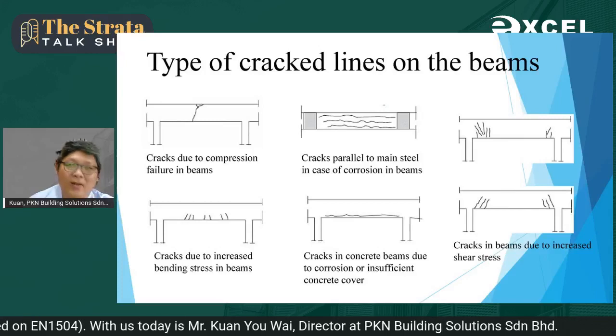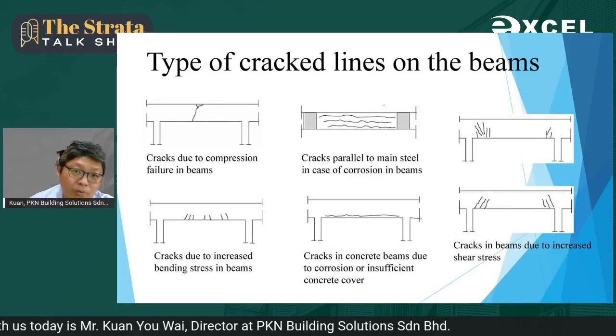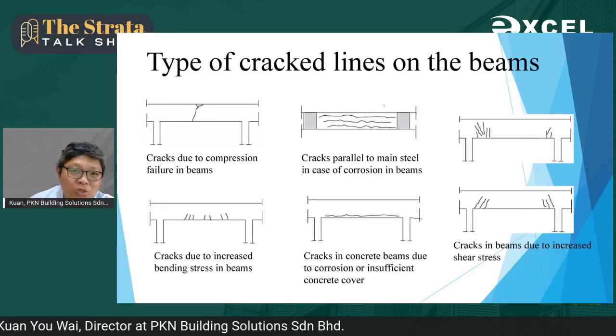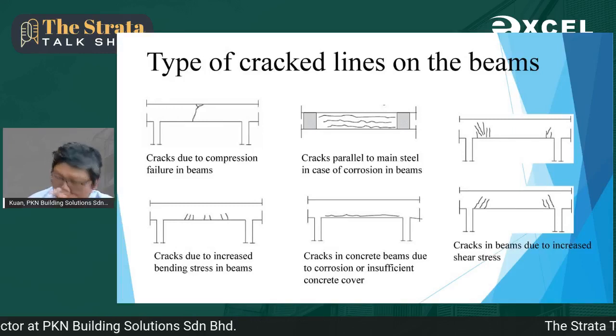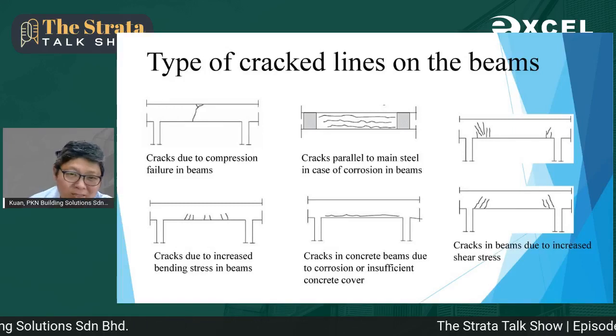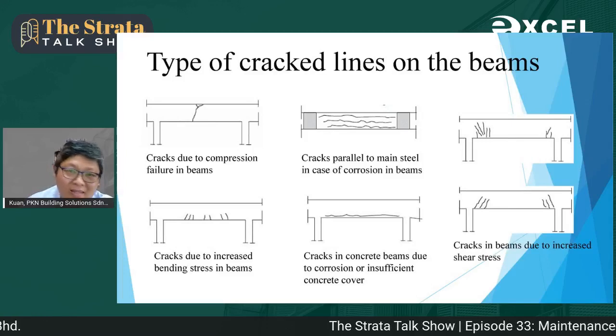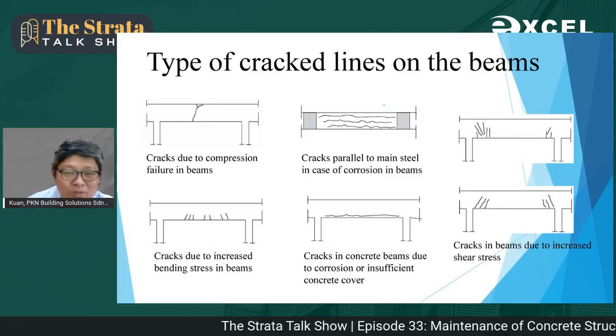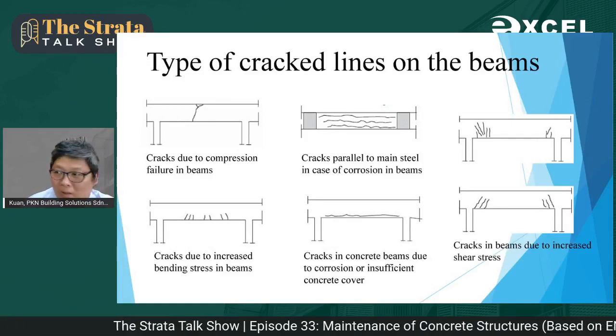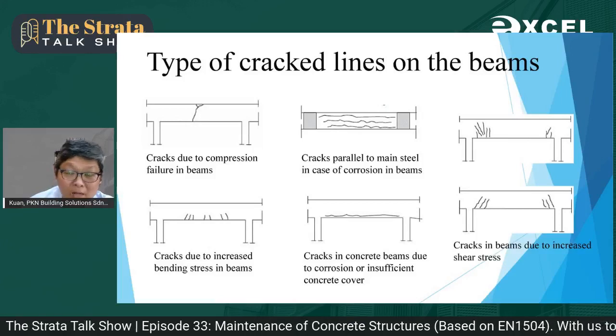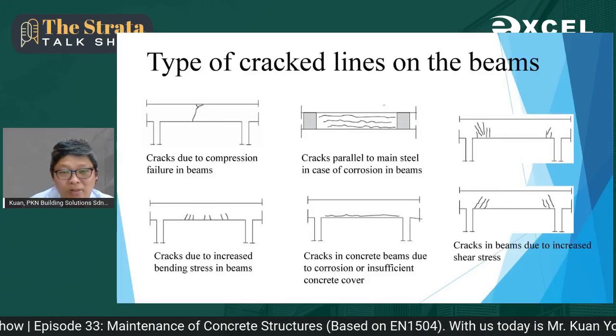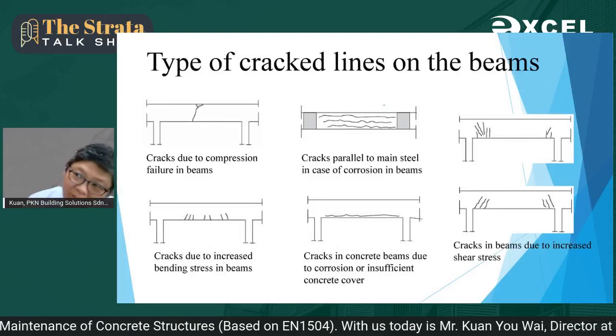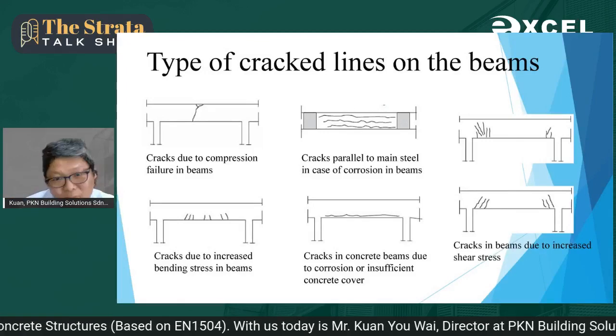the slightest crack. But for water to be able to travel in, it only needs 0.23 mm, which is equivalent to the thickness of your hair, for the water to be sucked into the concrete, simply because there's a lot of mineral in the concrete. The mineral will pull in the water through the osmosis process.